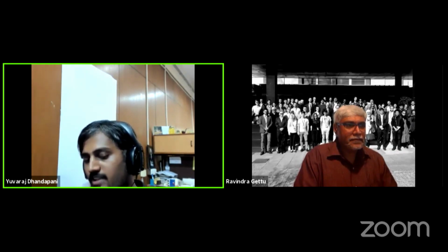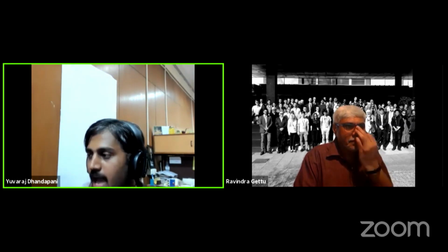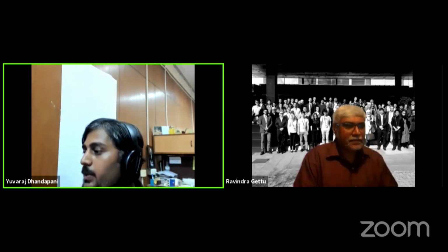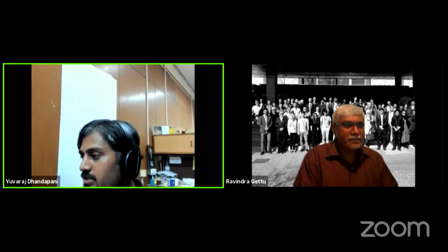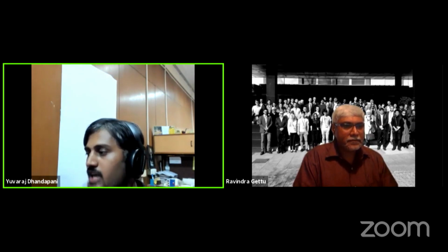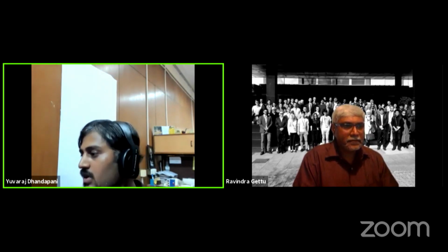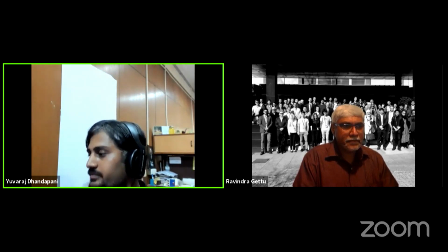But when you come to limestone, the major component is calcite particle, which makes limestone. And because of the calcium surfaces, it is going to allow nucleation of CSH to happen on the cement surface, which is why you see a major shift in the hydration curve when you start using limestone compared to quartz or even class F fly ash, which is a reactive material.